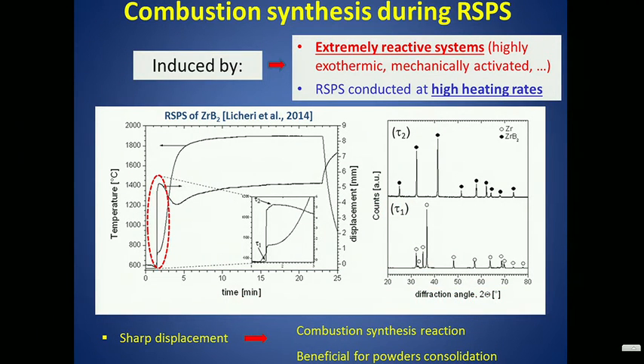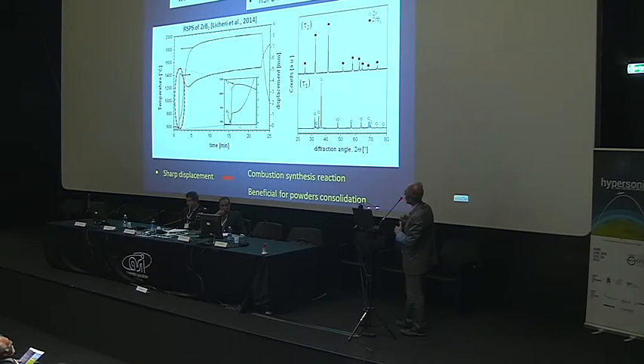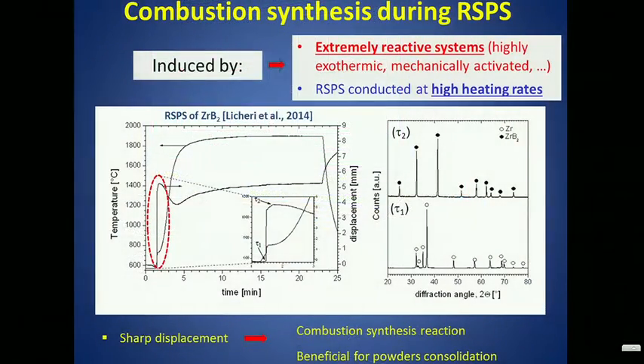Let me go to just another example, which probably is the last one. One more thing that you could do is, if you take a look at this zirconium diboride system, this is a very recent result. If you have an extremely reactive system, as this diboride is, then what you can see is that in a very short time, see tau 1, tau 2, the composition changes abruptly from, say, 1.5 minutes up to 1.7 minutes of synthesis. You do get such a difference, which is quite interesting from the scientific point of view also.